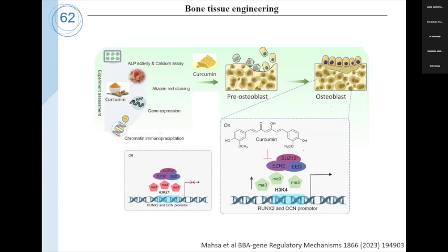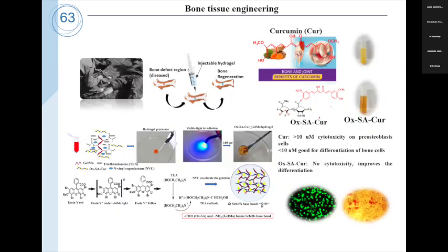However, as mentioned earlier, curcumin has poor water solubility and bioavailability to treat various bone diseases. So we prepared a curcumin conjugate, oxidized sodium alginate curcumin conjugate, in order to easily solubilize in the water. Then we prepared the injectable hydrogel by combining with gelatin methacrylate using visible light irradiation.